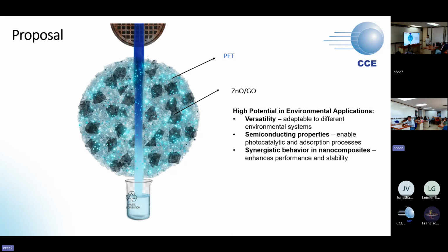Actually, the original idea was to mix three things: absorption, filtration, and photocatalysis, because zinc oxide presents a photocatalytic effect. However, when we incorporate the photocatalytic process, the process was very unstable. I don't know if you know, but when you do a photocatalytic process, first you study the absorption process. Once you reach the equilibrium state, you light on the lamps, and the photocatalytic process begins.